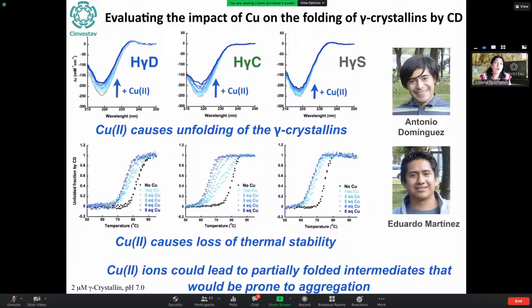was being lost. Then if we do thermal denaturation experiments, we can see these curves, the transition temperature, the Tm, being decreased to lower temperatures as we add more copper. So basically, this suggests that the metal ions are leading to loss of folding and also loss of thermal stability, and probably yielding the formation of partially folded intermediates that, of course, will be prone to aggregation.